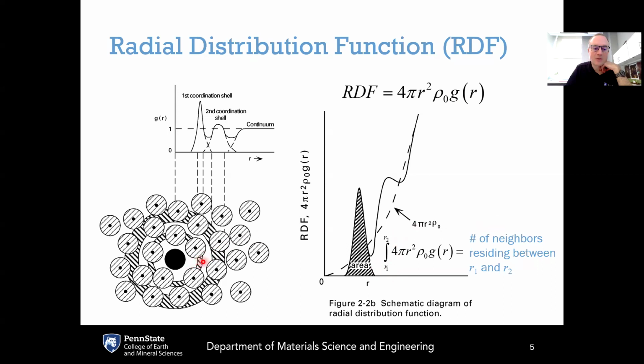If we've got R1 and R2 to define some range of R values there, and you integrate all of that, that integral would give you the number of neighbors that's expected, which for this particular diagram would be 5 atoms in that shell. If you do the same thing for the second nearest neighbor, integrating the RDF for that second nearest neighbor, that would give you the number of atoms found in the second nearest neighbor shell, and so on.